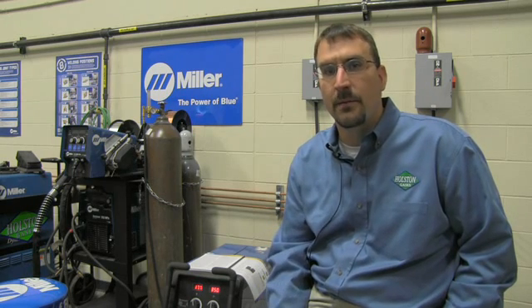So we'll be using a Miller-Matic 252 with a 75% argon, 25% CO2 shielding gas mixture, along with an 035 solid wire. Now, to speak real quickly on the shielding gas mixtures, keep in mind that there are many different types of shielding gases out there that can be used with short circuit transfer. The type of gas mixture that is used really depends on the application or the variety of applications in the shop. So, as long as you're using a 75% argon up to 95% argon with a balanced CO2, you should be in good shape. This should produce a very stable short circuit transfer.